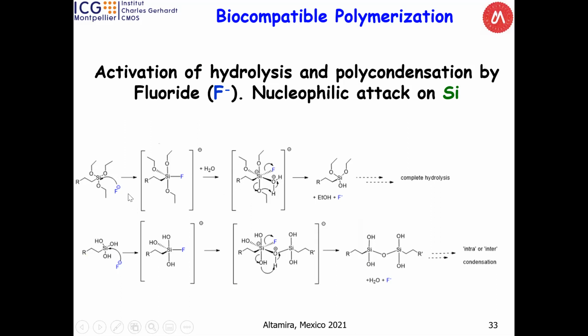So first one, activation, and then water can attack here. And then hydrolysis takes place. For polymerization, same scheme: attack of F minus and connection now between two hydroxy groups. This hydroxy group attacks the silicon center, maybe takes another one, it's the same, and then you get your siloxane and release of water and F minus, and so on.